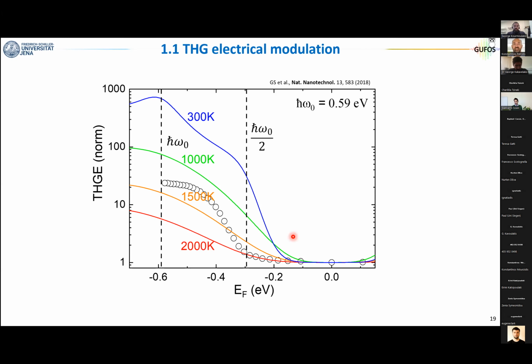The Chi1 plays a role because the fundamental beam is absorbed, and by absorption, it will increase the temperature. This increase in the temperature is what eventually changes the efficiency of the nonlinear process. And since we know that the absorption of graphene is also gate tunable, because by tuning the voltage you can move between intraband and interband absorption, you see that as we cross this point, the experimental data do not follow any theoretical curve. This is because the theoretical curves are done for a fixed temperature, while the real experimental temperature changes as you change the Fermi energy.